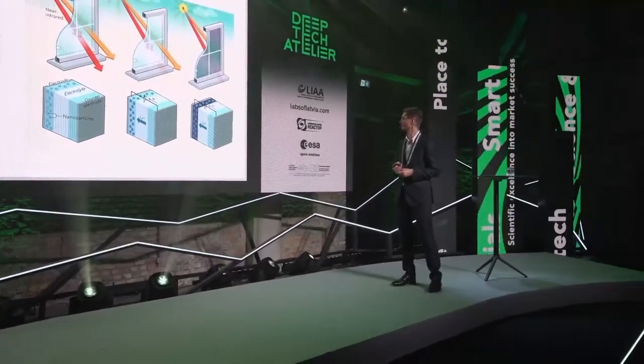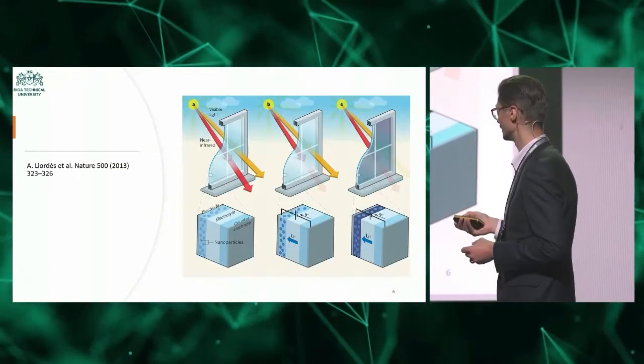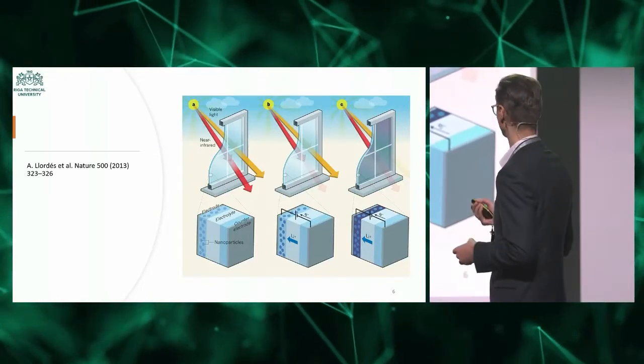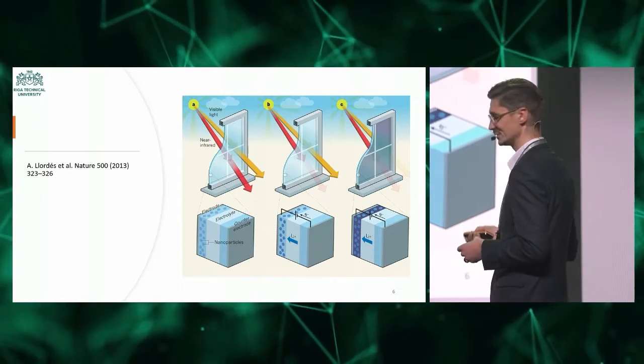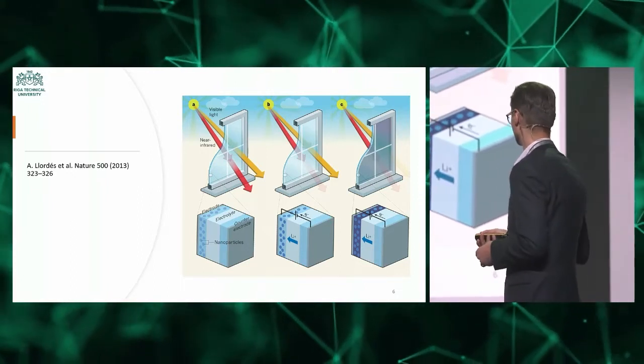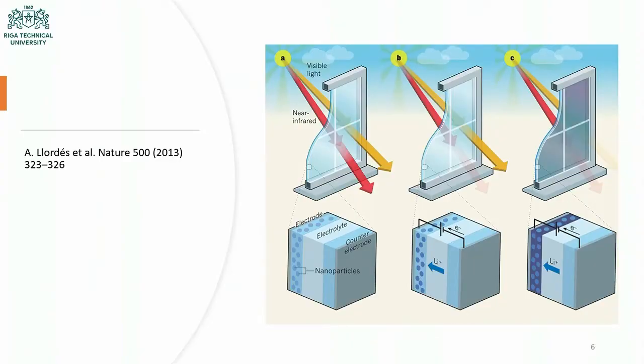A paper was published almost 10 years ago in Nature, where they proposed such a smart window device. This is still a benchmark in the field. Basically, they used a niobium glass matrix with indium tin oxide degenerated semiconductor quantum dots in there, and then lithium ions intercalate in this layer. In such a way you can control the charge carrier concentration in these nanocrystals, and this in turn influences the optical properties.